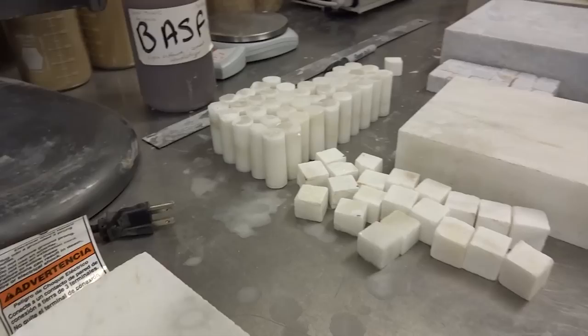The virtue of hydroxyapatite is that it's 10,000 times less soluble than marble. All we need to do is deposit a thin coating of the material on the surface of the marble, and it will provide years of protection. This treatment is very practical because it's water-based, the ingredients are non-toxic, they're not particularly expensive, and they're easy to apply.